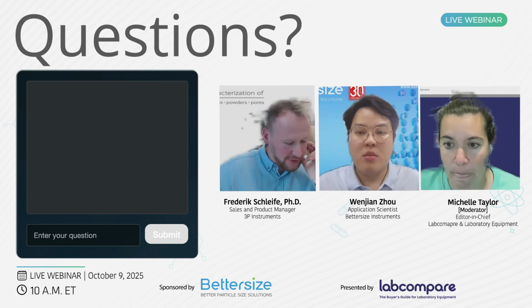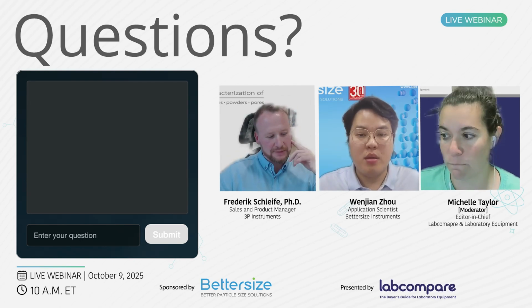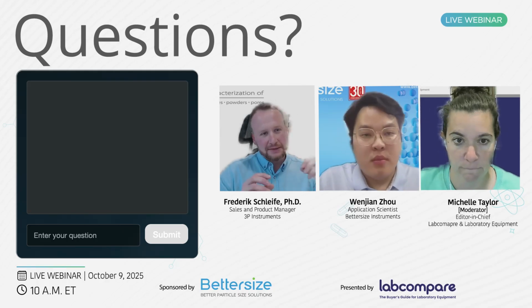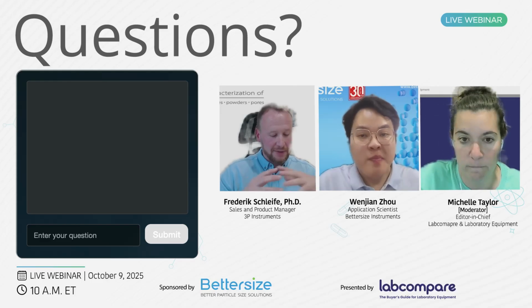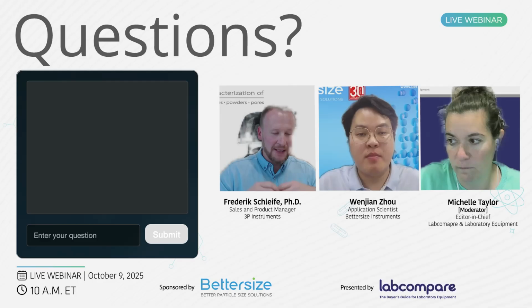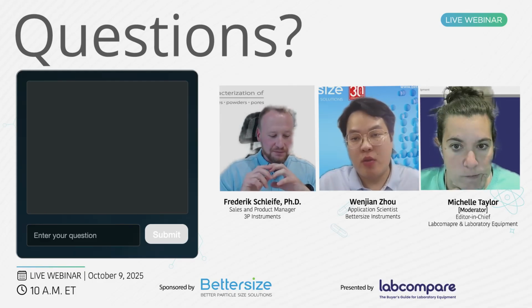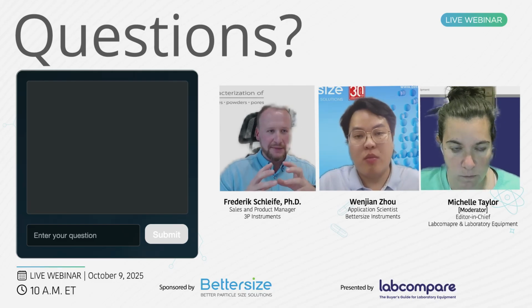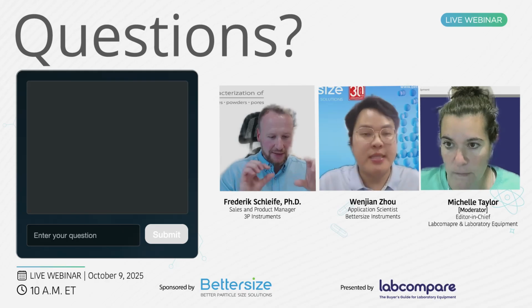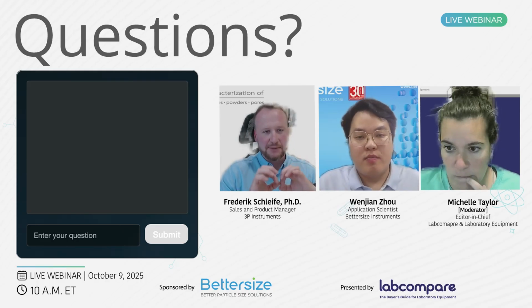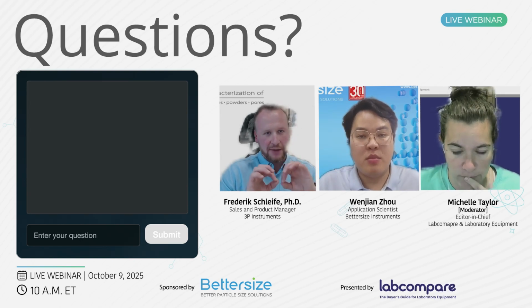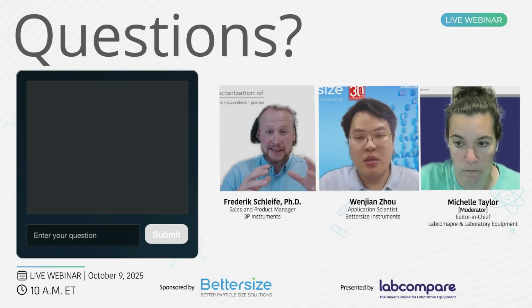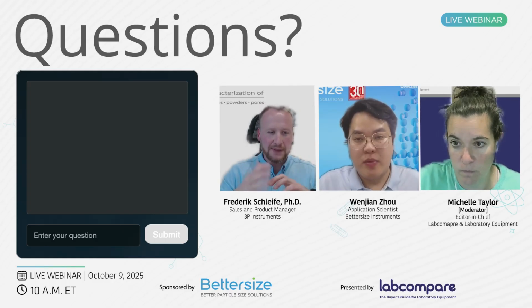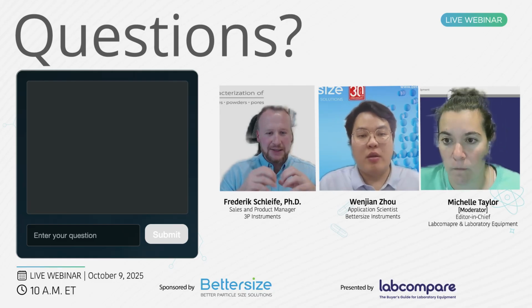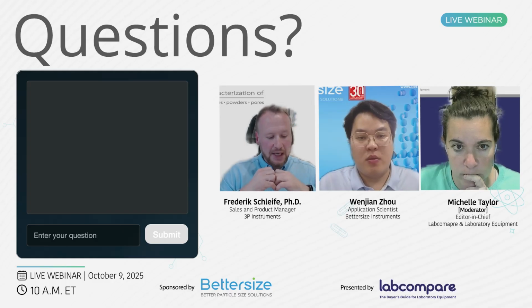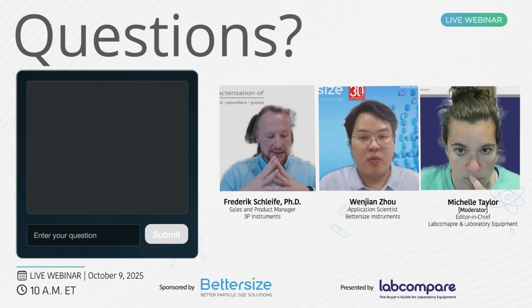Yeah, so that's a good question. Of course, this is something you would expect, as a higher amount of fine powder might result in even smaller pores in the green body. So maybe you get a lower sintering temperature or even a higher strength in the green body. But unfortunately, it's the opposite, because you would see an even lower green body density. And the reason is that, as I demonstrated, those fine powders will occupy the interparticle spaces between the larger particles. Once all the interparticle spaces of the larger particles are saturated, additional fine content would form layers around the larger particles. This leads to an even lower green body density, and also does not really have an effect on the sintering temperature.